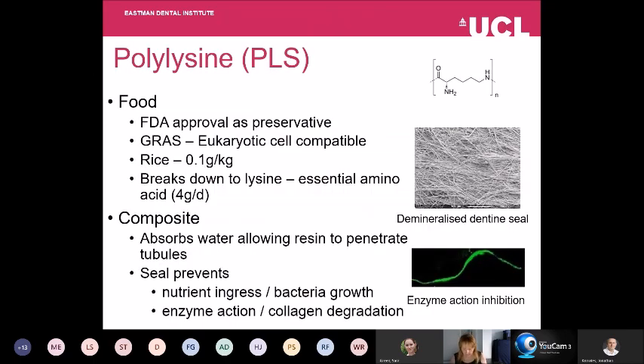So polylysine, our first additional component from food, it's got FDA approval as a preservative for food. And it's also got what's called GRAS status, that's generally recognised as safe. The reason for this is it is highly compatible with our eukaryotic cells. In fact, it's actually used in cell culture to get cells to grow on the surfaces of plastic. We can also find that it's added into a wide range of different foods, with rice being particularly common. It's added in at levels of around about 0.1 grams per kilogram.